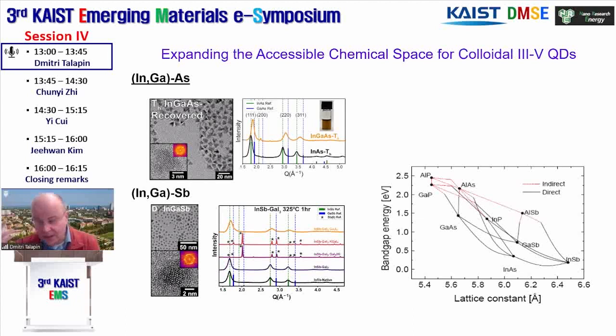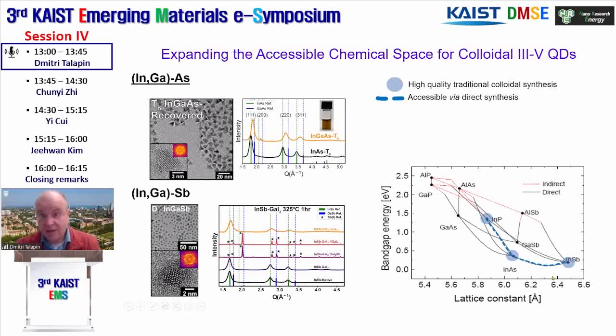And overall, in semiconductor engineering, especially in the space of III-V materials, we often rely on diagrams like this, where band gap or electronic structure is related to the lattice constants, and it allows us to map and couple properties of different III-V semiconductors. I want to use this plot to put you in the context of what we can and what we cannot do. By traditional solution synthesis using organic solvents, we could make indium phosphide, indium arsenide, and indium antimonide quantum dots. And with a little effort, we may be able to access mixed pnictide compositions.